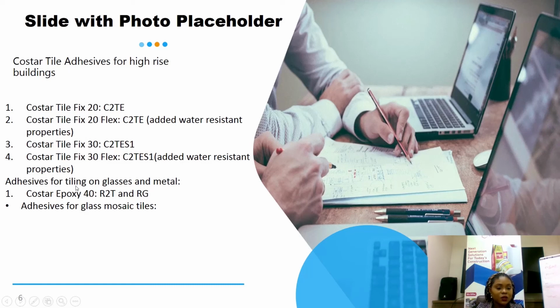We have adhesives for tiling on glass and metal, which is our Costar Epoxy 40. You can see that the standard on the classification is R2T and RG. So instead of cementitious, which we have the other classifications I will mention, this is epoxy based, resin based basically. So it has even increased tensile strength than cementitious adhesives, and it can be used as both adhesive and tile grout.